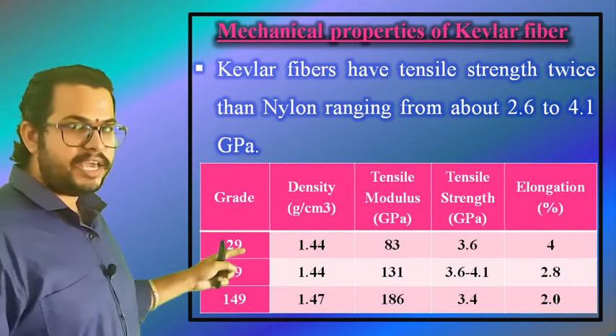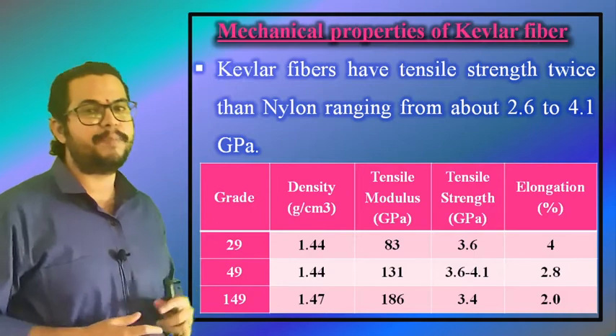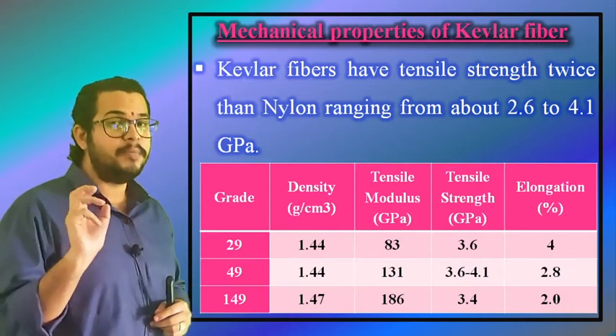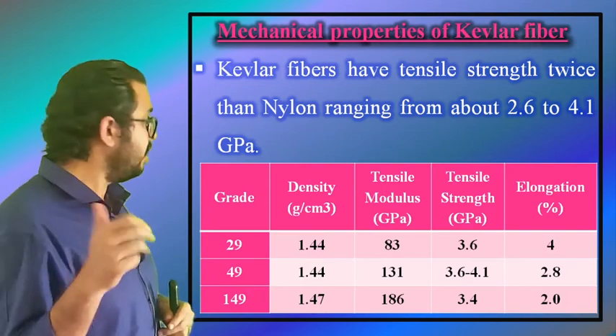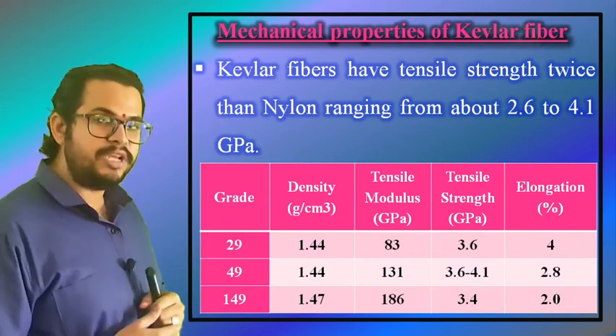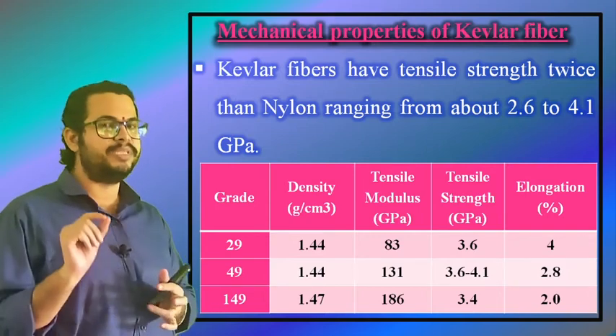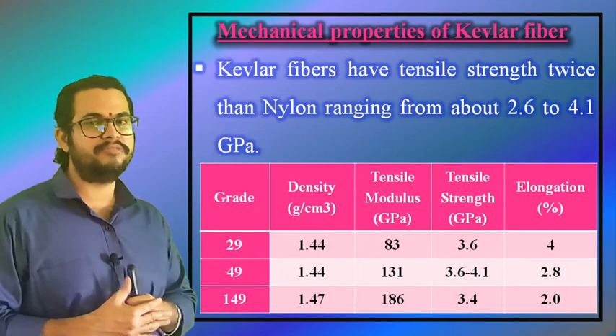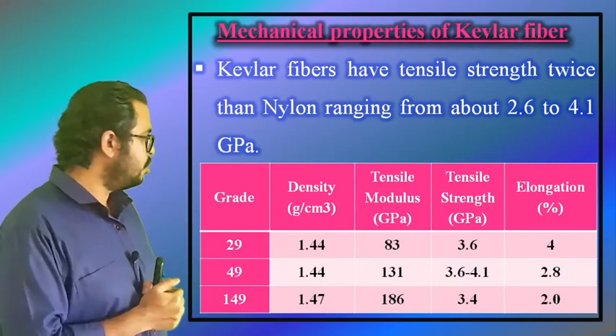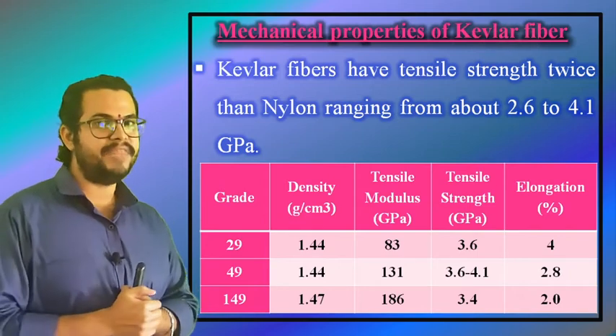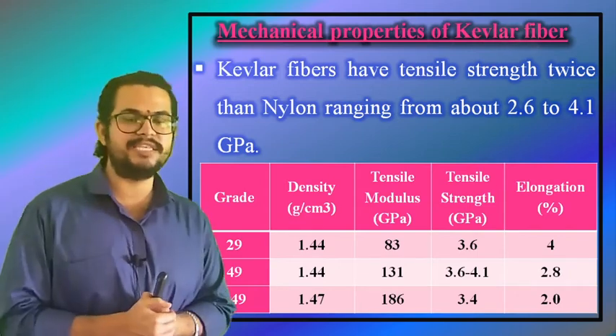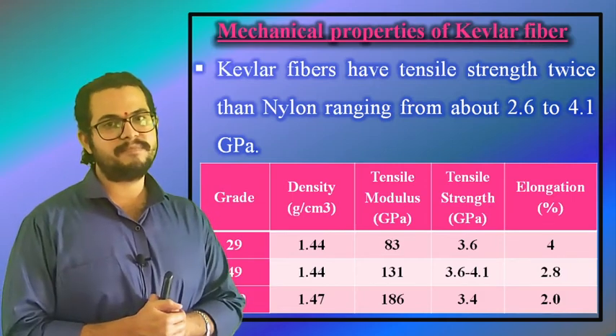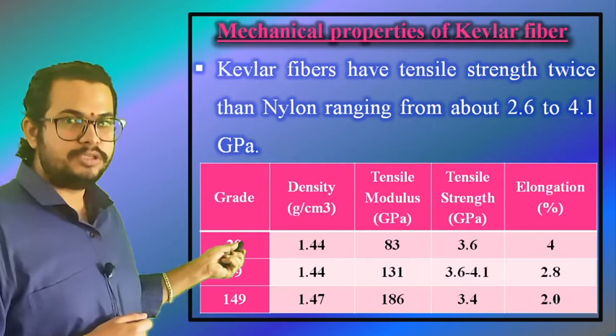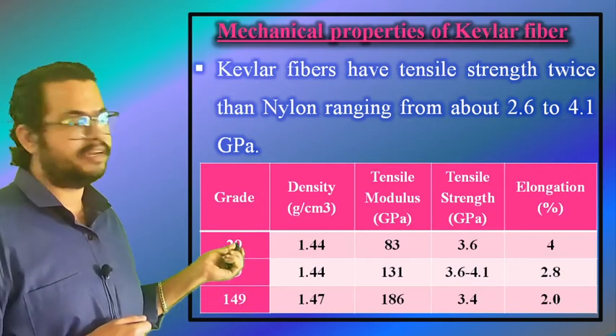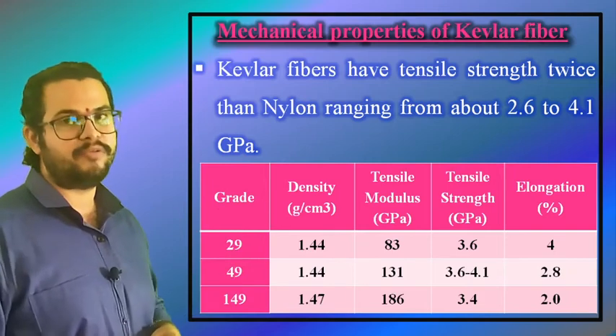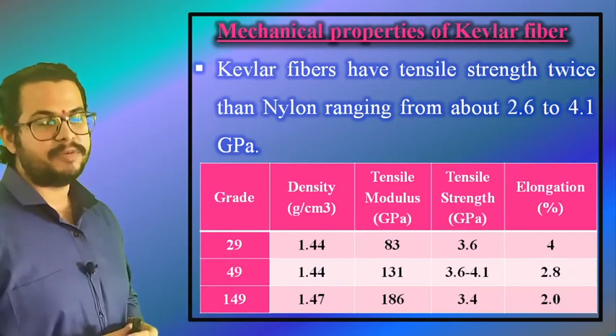That means the densities of all three types of Kevlar fibers are approximately the same. But when the tensile modulus is observed, we can understand that the modulus of 29 grade Kevlar fiber is the least with 83 gigapascals, and the tensile modulus of 149 grade Kevlar fiber is the highest with 186 gigapascals, while that of 49 grade Kevlar fiber is intermediate with 131 gigapascals. Similarly, the tensile strength is showcased as 3.6 gigapascals for 29 grade, and 3.6 and 3.4 gigapascals for the other two Kevlar fibers.